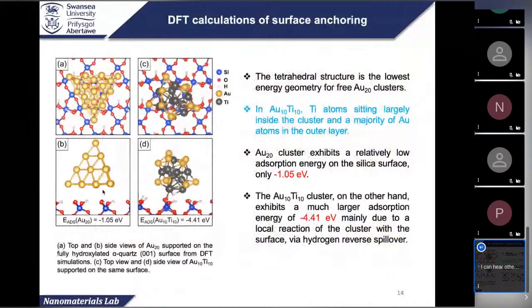The reason that gold titanium has an anchor effect is explained by the DFT calculations. Basically, if you alloy titanium with the gold on a silicon dioxide or silicon oxide surface, the energy of those particles with the surface becomes quite different. The titanium in the gold titanium cluster can establish a bond with the surface oxygen. This is where the anchor effect comes from. This increases the adsorption energy of the particle, making them stay in their position to resist sintering.